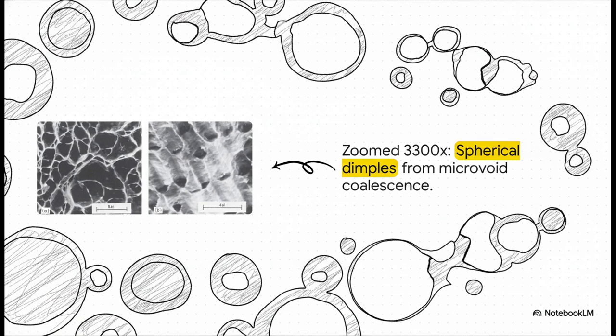When we interrogate the metal under a scanning electron microscope, magnified 3300 times, the fibrous central region of that ductile cup and cone fracture reveals these incredible textures. Look at those tiny spherical dimples. What you're actually looking at are the separated halves of those microvoids we just talked about. The metal pulled apart, the voids stretched to their limit, and they finally tore, leaving these little crater-like dimples behind.